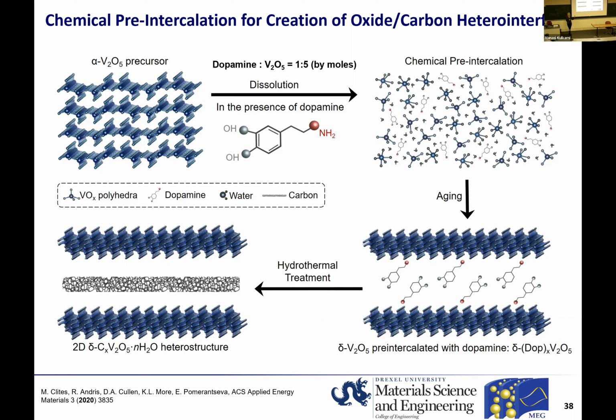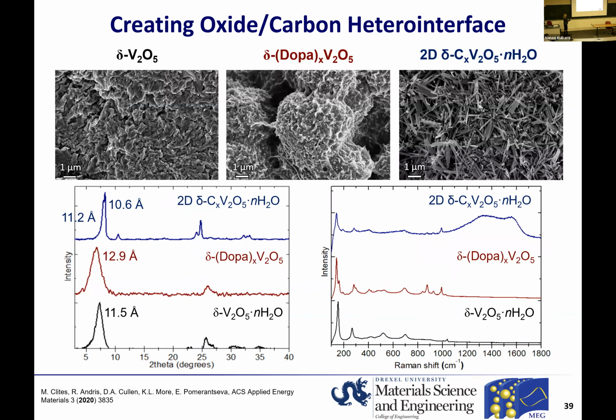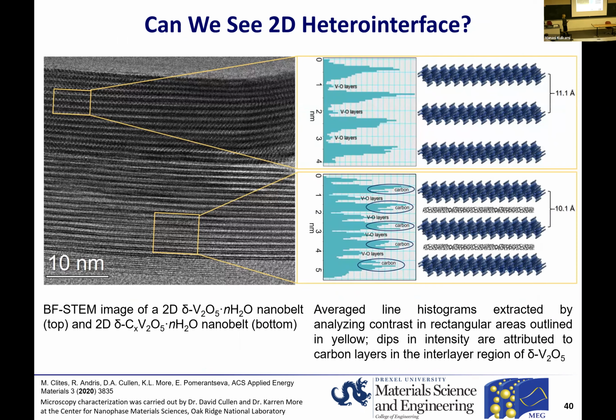We just for fun tried hydrothermal treatment, and we found that yes, we see some carbon bands in the Raman spectra of the product, which tells us that some carbonization occurred even during the hydrothermal treatment process. Of course, this is not graphitic carbon. This is something very amorphous, but still we thought it would be worth investigating electrochemical charge storage properties of this product. But before that, we also looked at the STEM imaging of this material, and we noticed that within a single particle, there are some regions where in the interlayer region, we see additional material forming.